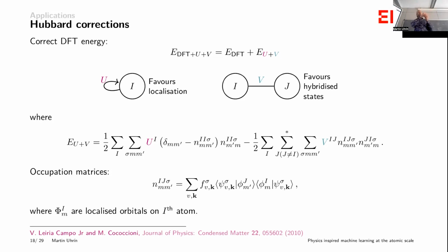So we know that these should be piecewise linear as you increase the amount of electrons, let's say, sitting on an atom by a tiny bit, not an integer amount, but a fractional amount. The DFT will actually give you a spurious curvature here, so a quadratic form. So we want to subtract that quadratic part to just leave a linear term, which we know from the physics is the correct thing to do. So that's why you see this term here. It's just NN. That's the quadratic part we're subtracting in the U, and same with the V, and we just leave a linear part, which is what this thing is doing.